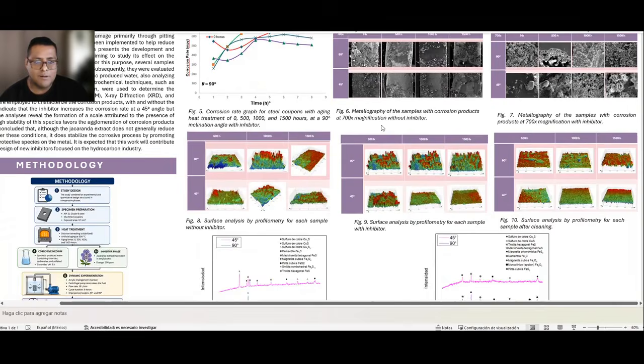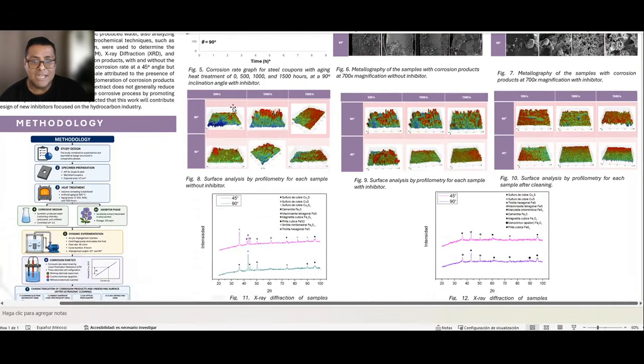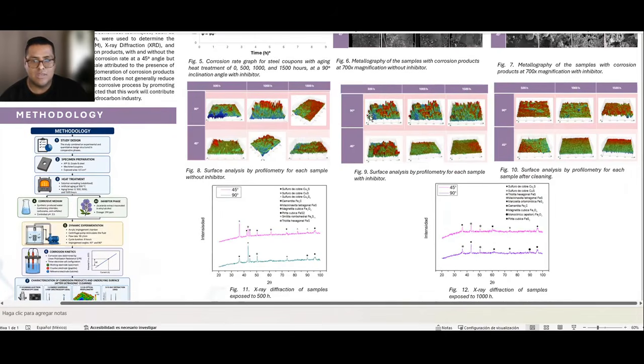And the 3D profilometry validates this mechanism perfectly. It showed deep valleys at 45 degrees and high accumulated crests at 90 degrees. However, after removing the layers with ultrasound, we could see severe directional growth and deep pitting underneath, especially for the longer aging times.